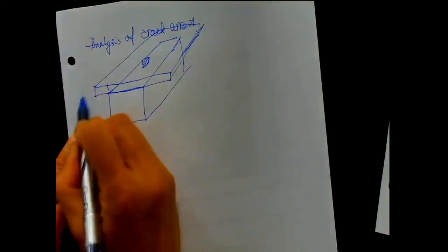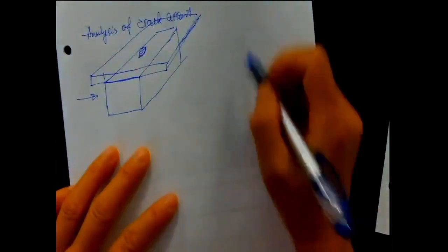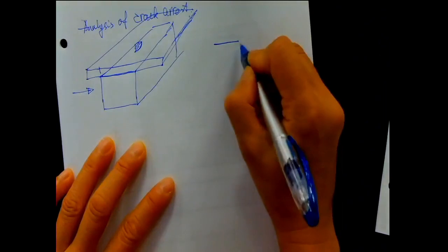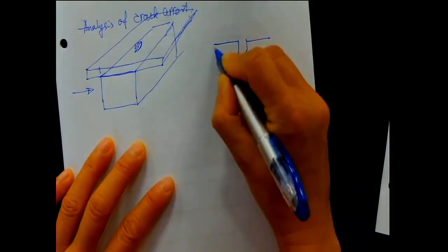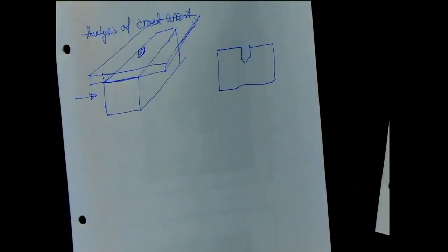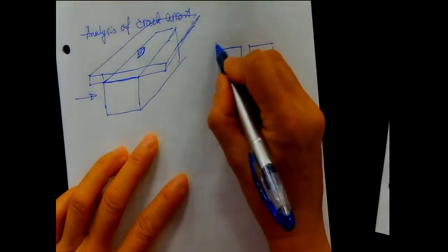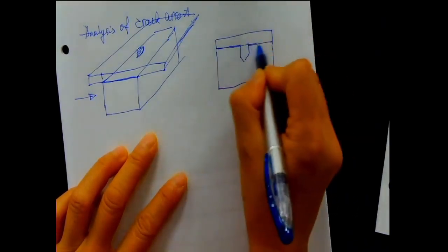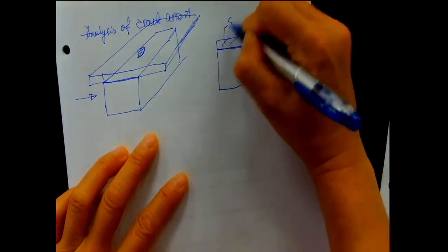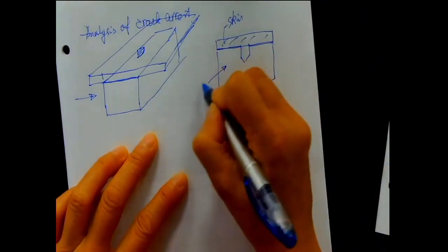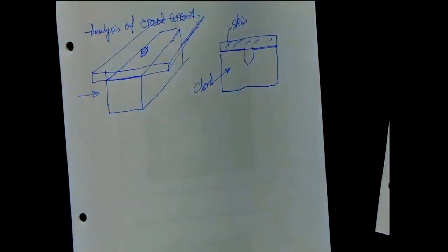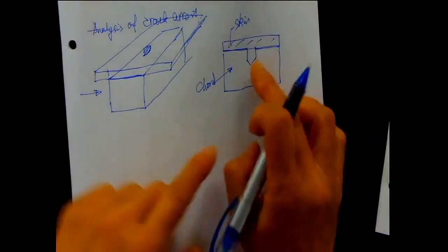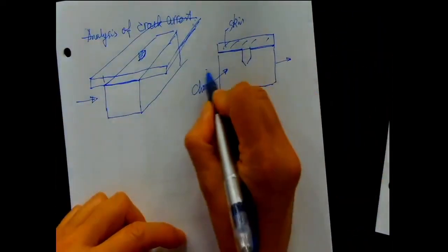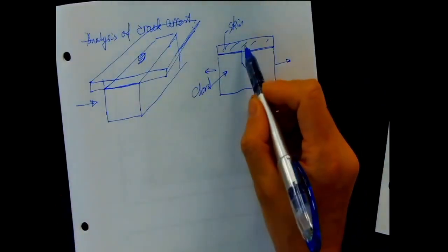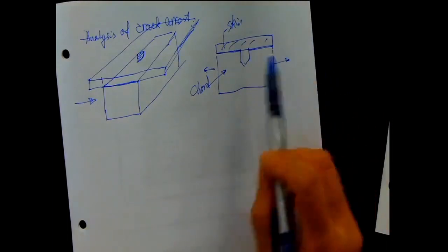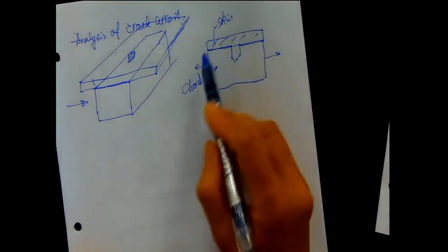So if I look from this side, what I see is I have a bar and I have a crack. Of course, I'm exaggerating the crack. And then on top, I have the skin that's holding it up. Okay? So if my crack wants to propagate over here as you load it, some load gets transferred over there. So the stress intensity will be a combination of this stress and the loading over there.